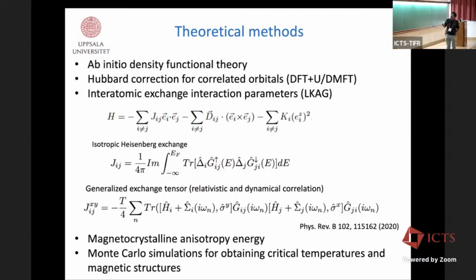The isotropic part is simply a very well known formula for many, many years. Then you can generalize this formula to extract the full exchange tensor, 3x3 tensor, when you include the relativistic effect with spin orbit coupling. Then you can also calculate the off-diagonal elements of this exchange tensor, which are important for extracting the Dzyaloshinskii-Moriya interaction parameters. And also at the same time, if you want to include the dynamical correlation effect, this formula gives you the XY component of this exchange tensor, where you see that you have self energies popping up here. These self energies come due to the dynamical correlation effects, which is a function of some Matsubara frequencies. Anyway, this formula is the most general formula that is used to calculate the full exchange tensor within dynamical mean field theory.